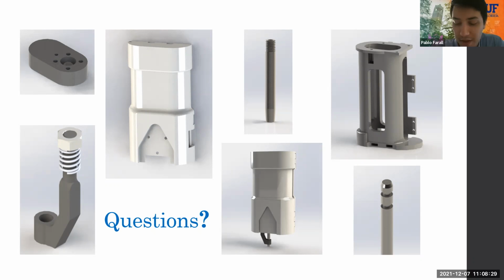Yeah, so honestly, we think that that could have happened due to a couple of reasons. The seal was not a problem because we thought at the beginning that would be the most difficult part to achieve, that seal with the O-rings, but it would hold the liquid every time. But we don't know if it's an actual issue with the scale or that testing equipment we were using, because sometimes it would be within 1 microliter, but then after we repeated the test 10 times for a single volume, it would fluctuate a little. So that's why we decided to just report the 5 microliter accuracy, because that was what we actually could repeat every time.